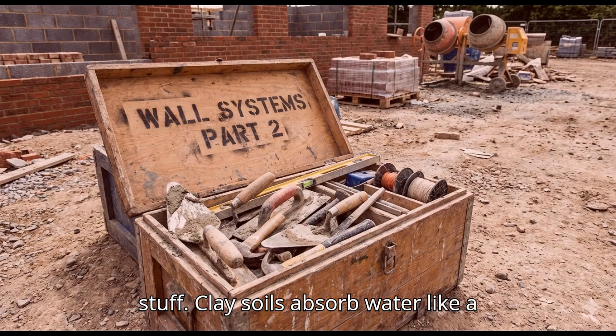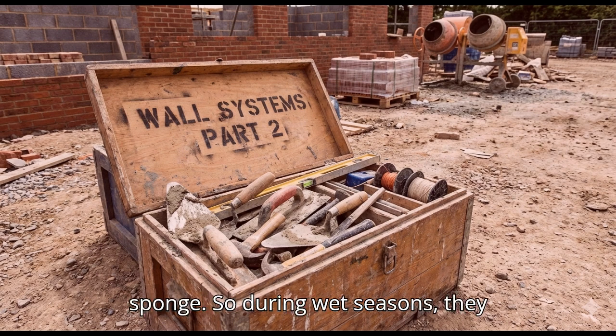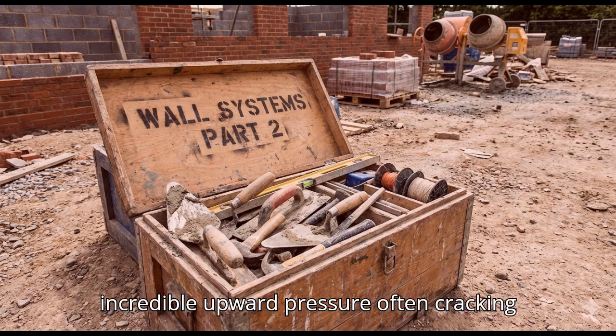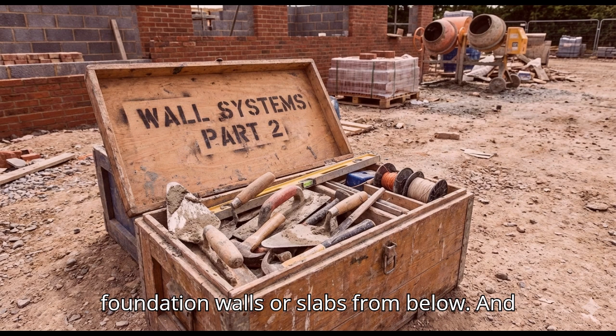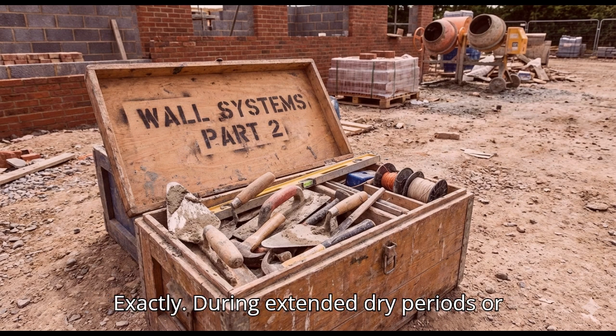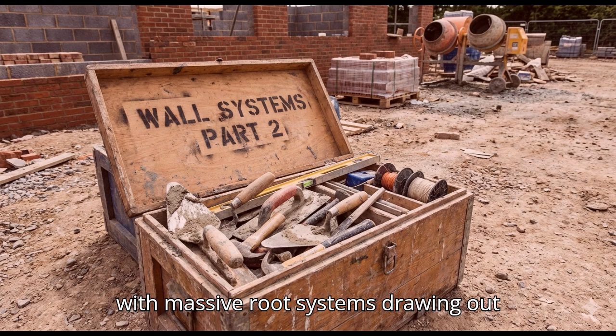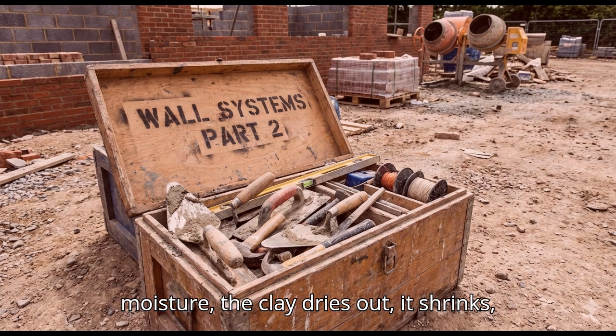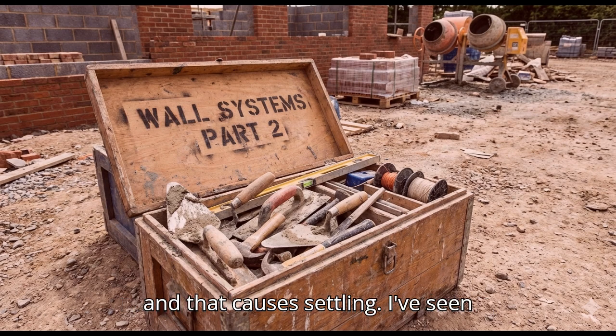Clay soils absorb water like a sponge. So during wet seasons, they expand significantly. That expansion causes heaving, which exerts this incredible upward pressure, often cracking foundation walls or slabs from below. And then the opposite happens in the summer. Exactly. During extended dry periods, or maybe you have big mature trees nearby with massive root systems drawing out moisture, the clay dries out, it shrinks, and that causes settling. I've seen cracks run diagonally clean up a wall because one corner of the building settled 2 inches while the rest of it just stayed put.